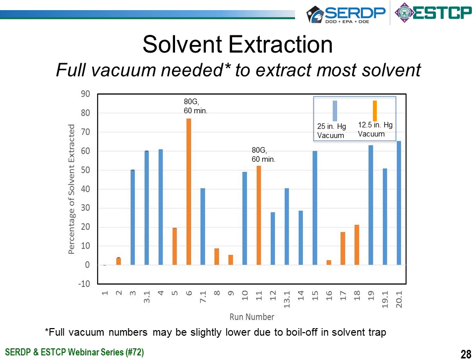When we look at the solvent extraction, the blue lines are the full vacuum at 25 inches of mercury, and the orange lines are the 12.5 inches of mercury half vacuum. As you can see, we collected the most amount of solvent when we used the full vacuum for the run.